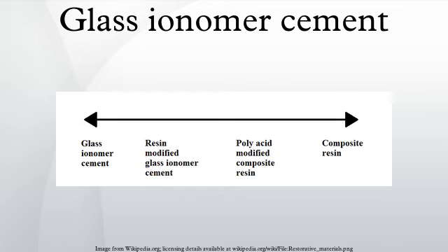Bonding between the cement and dental hard tissues is achieved through an ionic exchange at the interface. Polyalkenoic chains enter the molecular surface of dental apatite, replacing phosphate ions. Calcium ions are displaced equally with the phosphate ions so as to maintain electrical equilibrium. This leads to the development of an ion-enriched layer of cement that is firmly attached to the tooth.